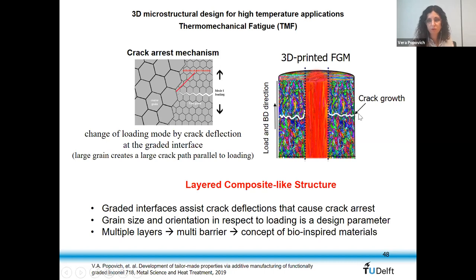So we tackle the fatigue at the outside, so the initiation is retarded, but once the crack has initiated, most importantly, it has no driving force anymore, because a crack would tend to propagate in the direction perpendicular, supposedly, to the load axis. And there's no driving force or it slows down, so it's a crack arrest that happens at the interface with this approach. So this is just something that I thought might be interesting for you guys to know, what kind of newer developments in additive technology are happening.